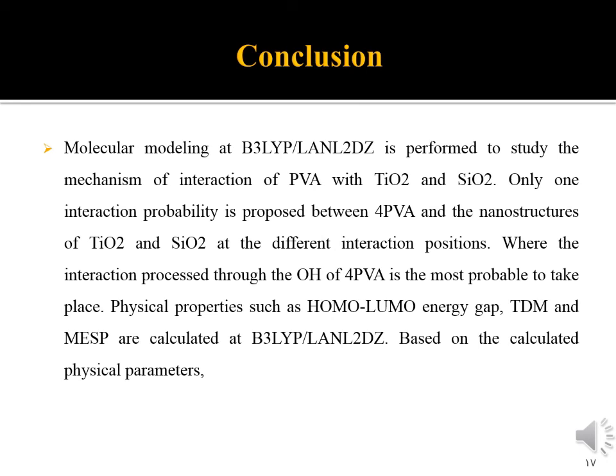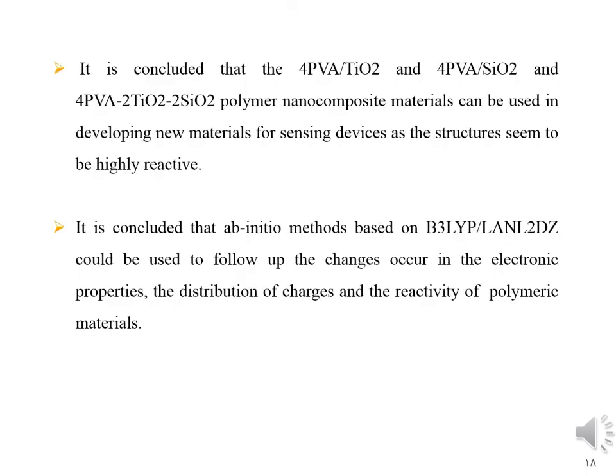Conclusion. Molecular modeling at the B3LYP level with basis set LANL2DZ is performed to study the mechanism of interaction of polyvinyl alcohol with titanium dioxide and silicon dioxide. It's concluded that the polyvinyl alcohol titanium dioxide, polyvinyl alcohol silicon dioxide, and polyvinyl alcohol to titanium dioxide to silicon dioxide polymer nanocomposite materials can be used in developing new materials for sensing devices as the structures seem to be highly reactive. It's concluded that ab initio methods based on B3LYP with basis set LANL2DZ could be used to follow up the changes that occur in the electronic properties, the distribution of charges, and the reactivity of polymeric materials.